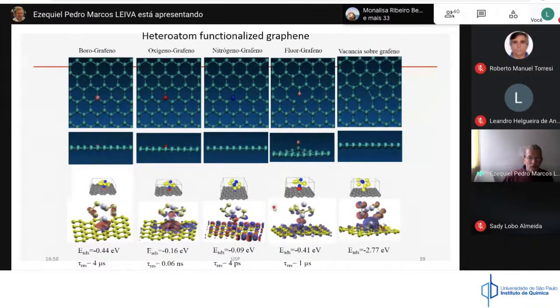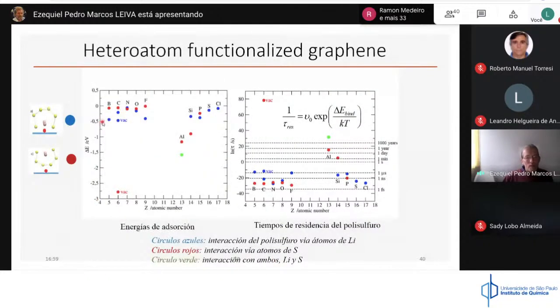And you can see that for none of these systems do you get a reasonable trapping time of the polysulfide on the surface. We considered many types of atoms: boron, carbon, nitrogen, oxygen, fluorine, aluminum, silicon, phosphorus, sulfur, and chlorine, and we found that the only good candidate is aluminum. Here you have the energy as a function of the atomic number, or you can also plot the logarithm of the retention time as a function of the atomic number.